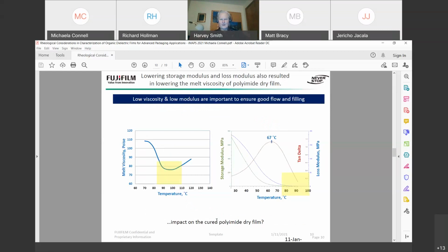So lowering the storage modulus and loss modulus also resulted in lowering the melt viscosity of the polyimide dry film. Low melt viscosity and low modulus are important to ensure good flow and filling. Based on these results, it is clear that we were successfully able to favorably alter the rheological properties for this application.